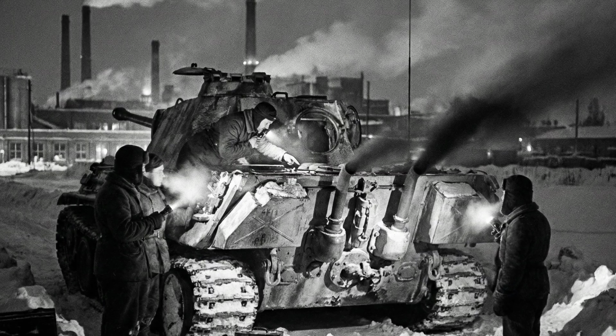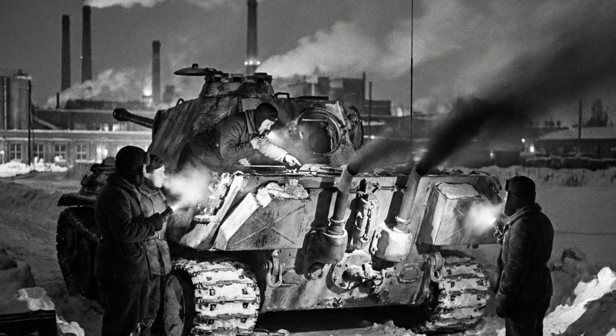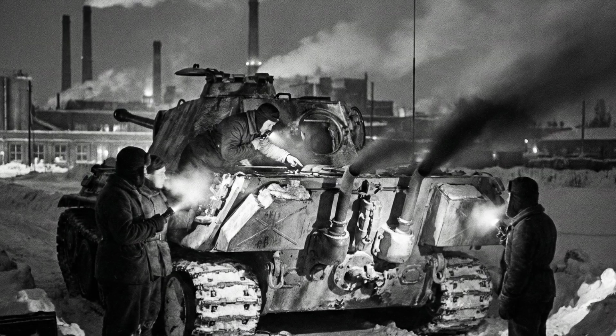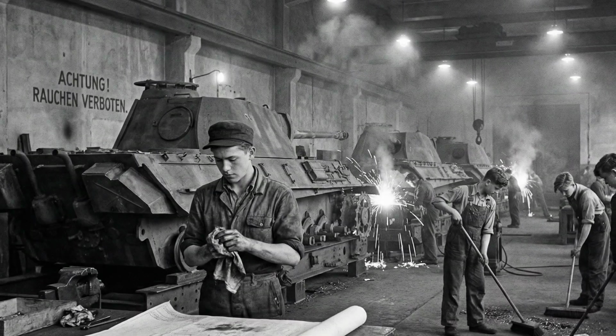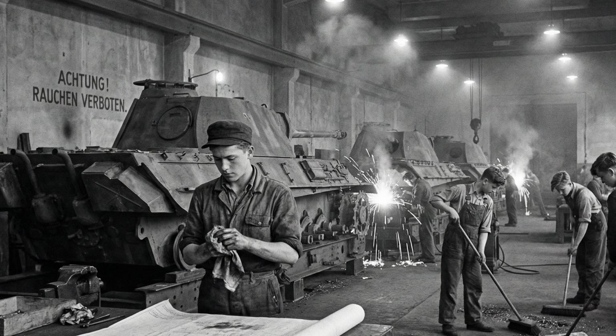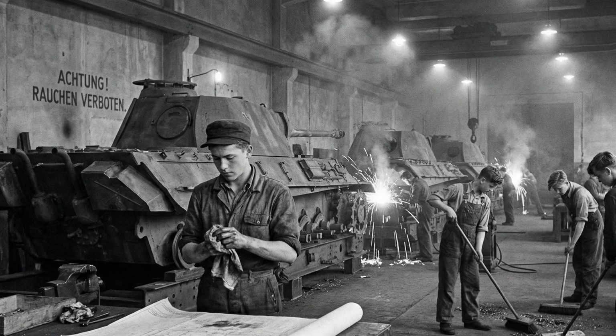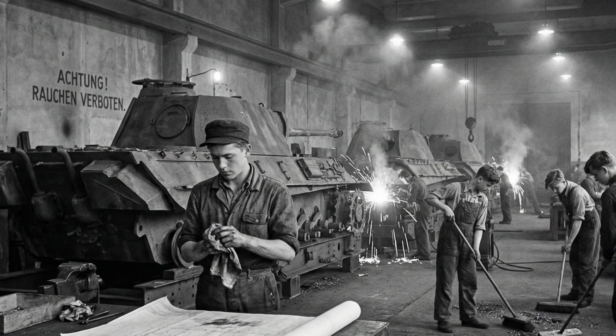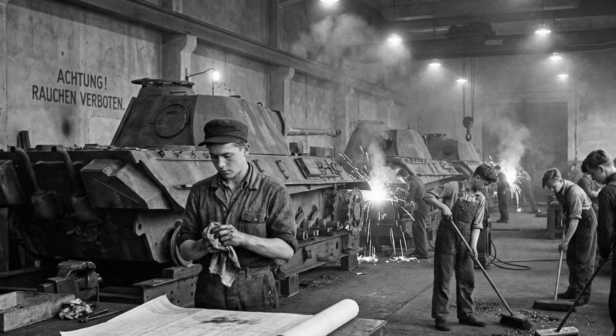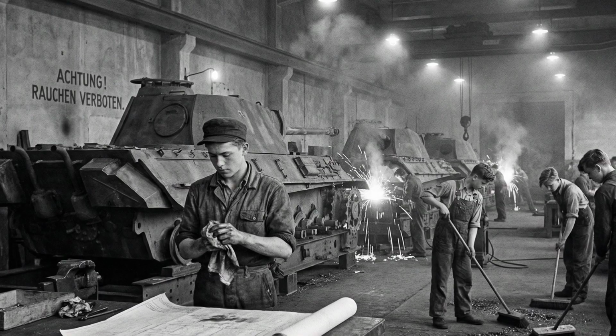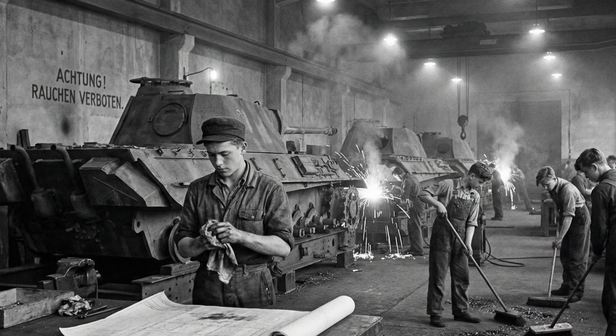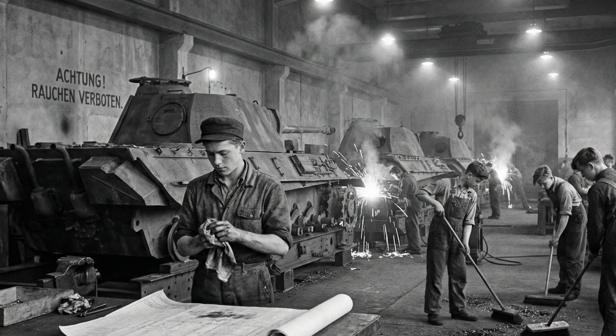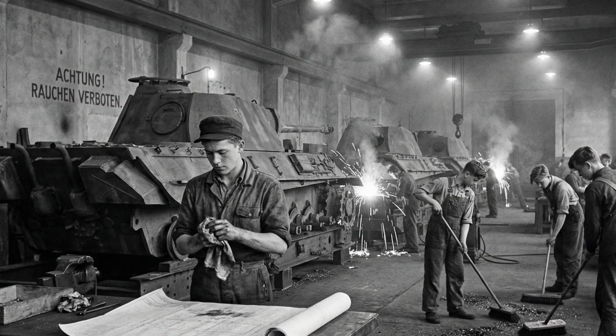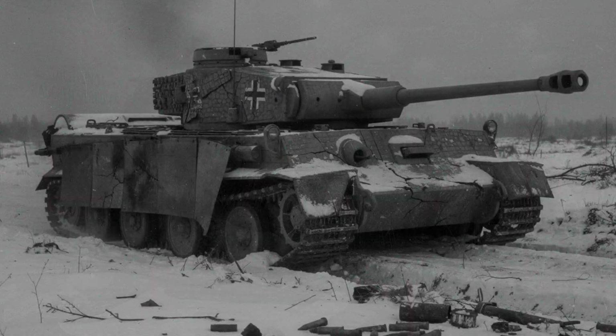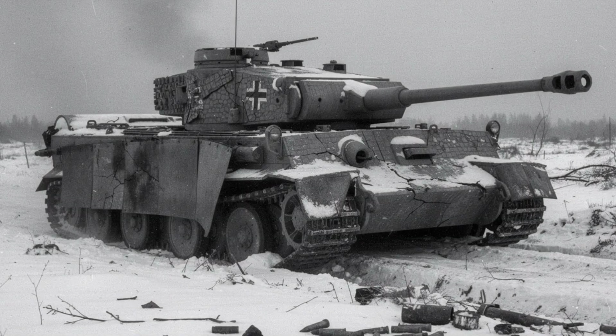The hull alone shows the equation. An 80mm glacis plate sloped at 55 degrees had to meet side plates without gaps. The interlock required precise milling and a controlled weld sequence. Weld too hot and distortion warped the fit. Weld too cold and porosity weakened the joint. Dieter wrote sequences on the wall. Clamp order ABC, preheat to target. Pause between passes. These steps slowed throughput but protected integrity.